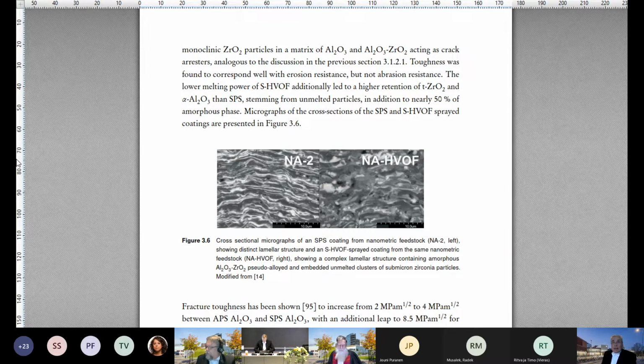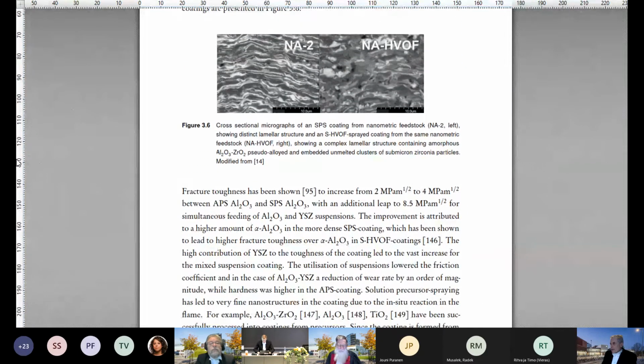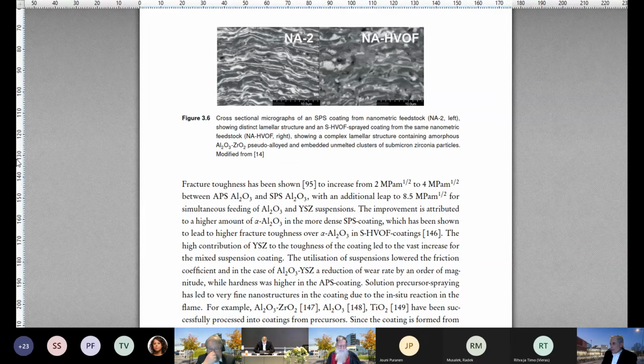I think you have similar images in your publication. Some of the nanomaterials actually make an agglomerate and they fly along with the particles, and they land as an agglomerate and most likely have the nanostructures within. I may still continue a little bit. Still under this image 3.6, there is this fracture toughness increase. There are significant numbers related to nano and this improvement with different nano materials included. So there's really an increase in toughness values. So it seems like a very attractive field, nevertheless.